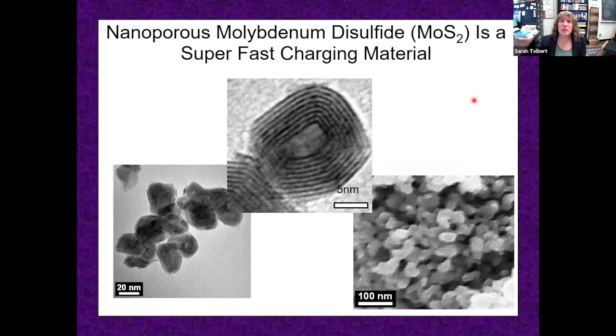Okay, let's look at another system that's also a super fast charging system. This one, again, is based on molybdenum, but this time we make a sulfide, not an oxide. For those of you who think about chemistry, sulfur is a big atom, it's sort of blobby. It doesn't really interact with lithium very well. And so lithium can move very quickly between the layers of moly sulfide.